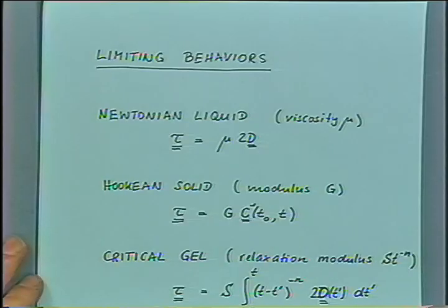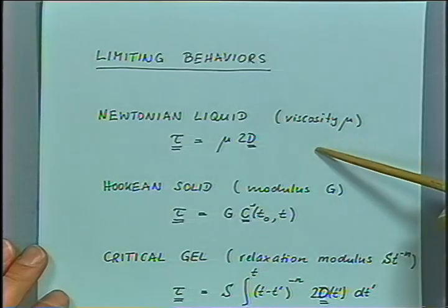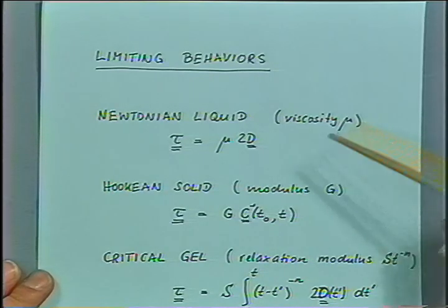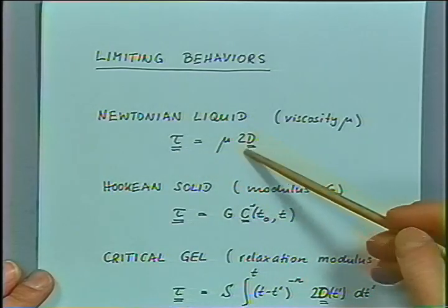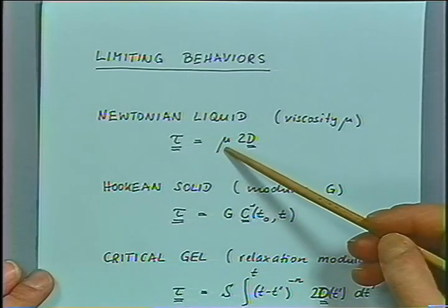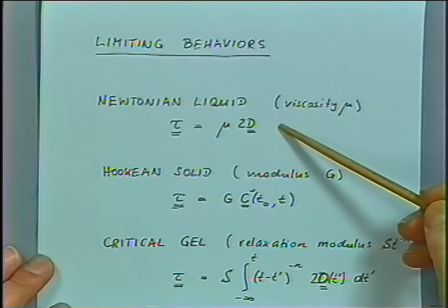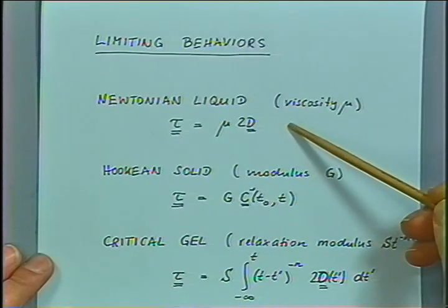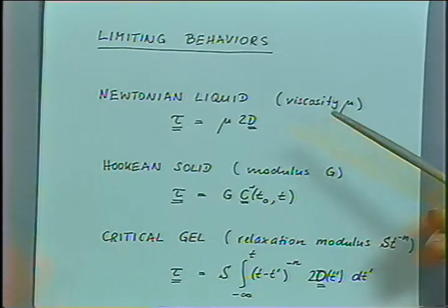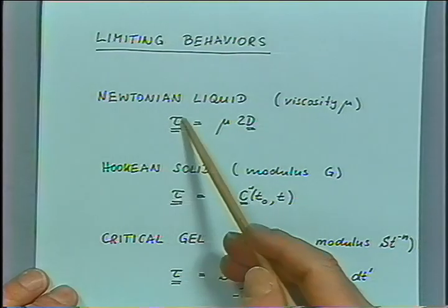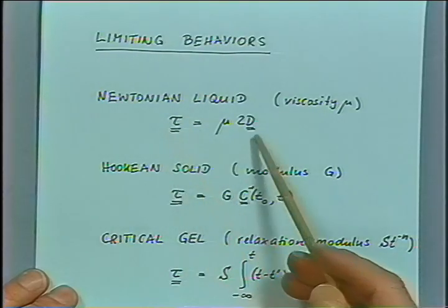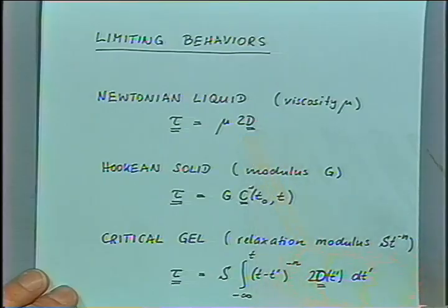Now, limiting behaviors typical of those constitutive equations are the Newtonian liquid for low molecular weight liquids. The only parameter is the viscosity. In there, the stress is proportional to the rate of deformation. The coefficient is the viscosity. Density changes are not mentioned here, but you could formulate an equation for a compressible Newtonian liquid. Note that I already took the deviatoric stress to describe this Newtonian behavior.